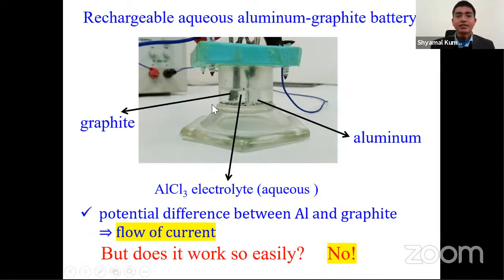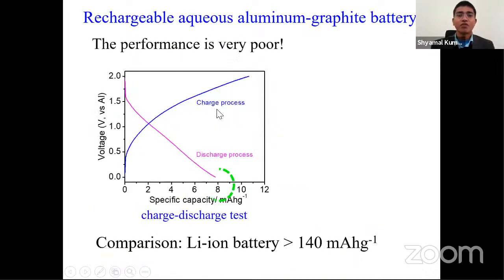Now, if it is a battery, does it work so easily? The answer is no. Why am I saying no? Because when we performed the electrochemical investigation to see how good it is, we saw that during the discharge process of the battery, that means when you are drawing current from the battery, we see a specific capacity of only 8 milliampere hour per gram. However, for comparison, I have noted down here that for a lithium-ion battery, this number is more than 140 milliampere hour per gram. So in comparison to a lithium-ion battery, obviously our aluminum graphite system is very inferior in terms of performance. So we pose 2 questions again: why is it showing poor performance, and how to improve it.